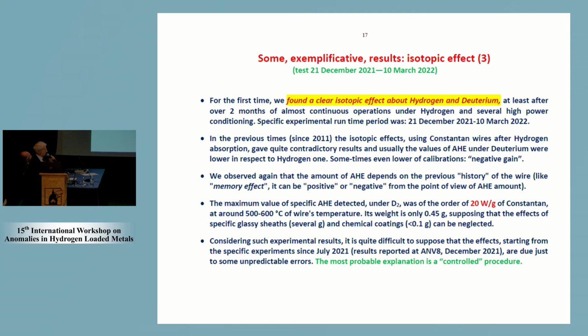Moreover, we were lucky: the first time, we were able to demonstrate that using deuterium with constantan, the AHE is larger with respect to hydrogen. Now, in all our previous experiments since 2011-12, when we moved from hydrogen to deuterium, the AHE almost disappeared or even went negative.